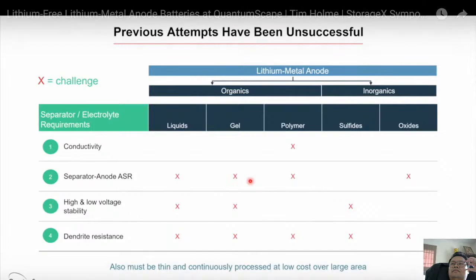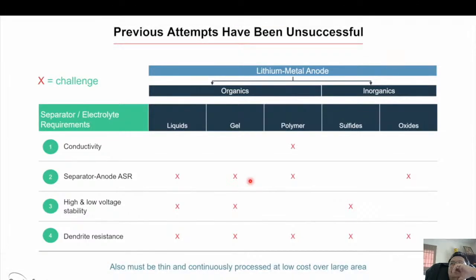Now, as I said, we didn't invent the lithium metal anode. That concept has been around for decades, but it has been hard to commercialize, and this is why you don't see a lot of cars today driving around with lithium metal anodes. So people have tried various different separator chemistries between organics and inorganics. There are many families of materials that have been attempted to work with lithium metal: liquids, gels, solid polymers like PEO. Among inorganics, there are sulfides and oxides are the most popular classes. Also emerging over the last few years are halides, borohydrides. Unfortunately, all of the materials that have been tried have real challenges on at least one, if not more, of the key metrics for the separator.